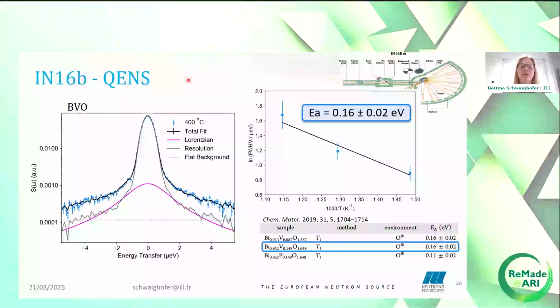For BVO, we obtain an activation energy of 0.16 electron volts, which is in great agreement with NMR data and suggests that on IN16B we're observing dynamics in the bismuth oxygen sublattice. For BPO, however, the temperature dependence was very weak, so we were not able to extract an activation energy from this.